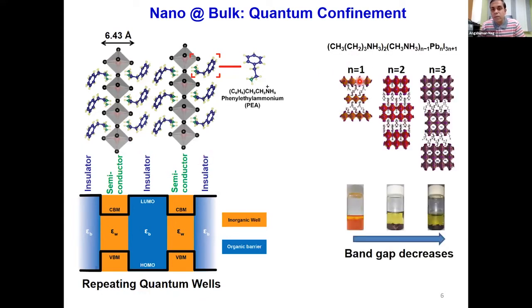And if you want to tune the extent of quantum confinement, you can do so by changing the thickness of the inorganic layer. So this is the generic formula. And if you increase n, the thickness of the inorganic layer increases. And that's how you see the band gap decreases, because the quantum confinement effect decreases with increase in the thickness of the inorganic layers. So this kind of system with n equal to 1 was studied pretty extensively in the 1980s and 90s by many groups, including the group of David Mitzi, and from 2015-16 onwards, other groups, including the group of Mercouri Kanatzidis, have studied layers with n equal to 2, 3, and higher n values.